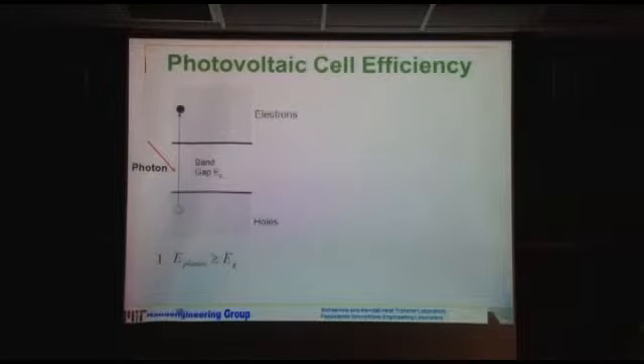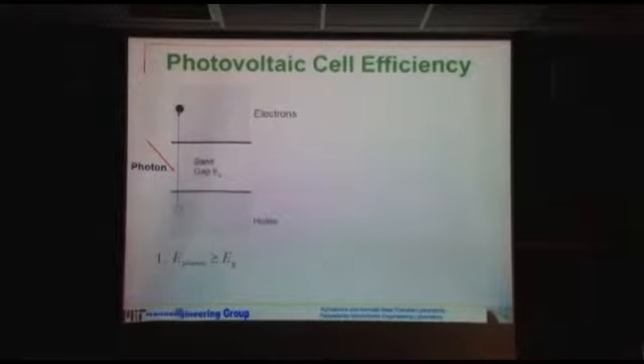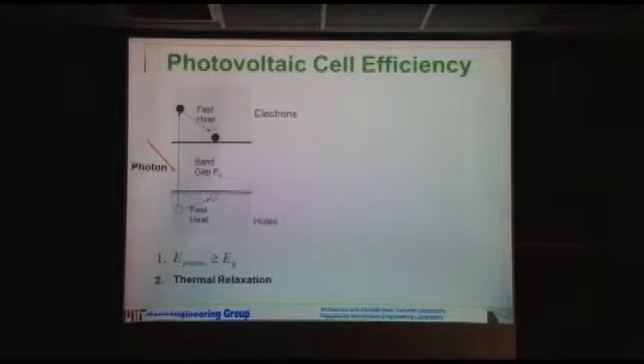And it turns out it's very hard to collect this high energy electron because there are atoms jiggling in the semiconductor. They will collide with this electron and quickly release part of this energy to fall to the edge of what we call the conduction band. And what's left behind is an empty hole, and that also falls to the edge. That means it generates heat. And this part of the heat in the solar cell is not useful, and we cannot collect it. So in this process, we lose part of the energy.